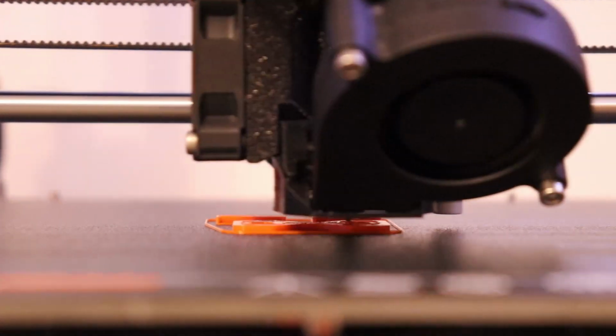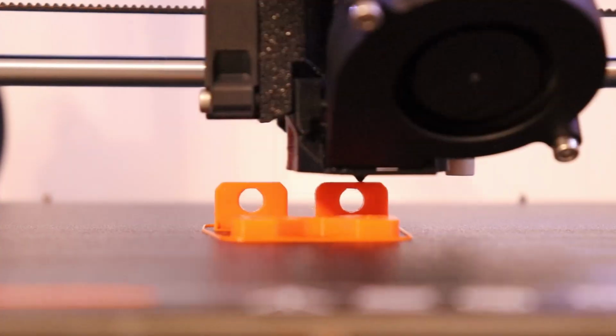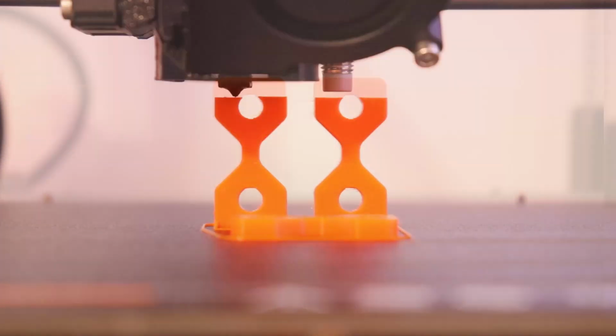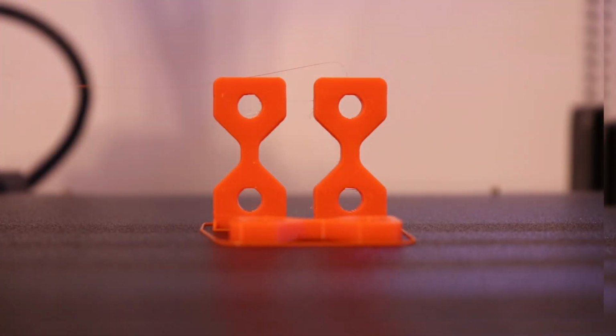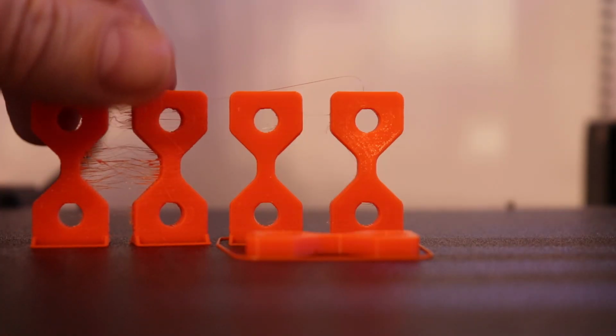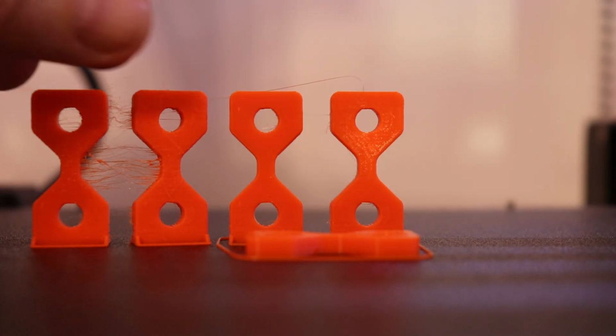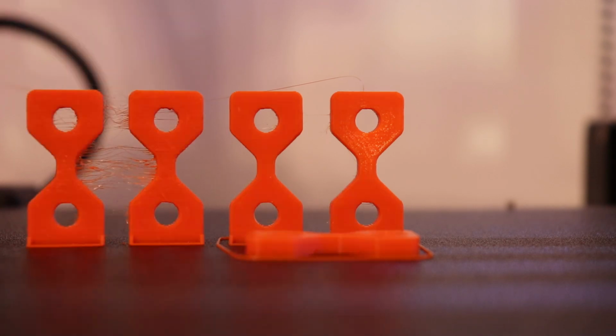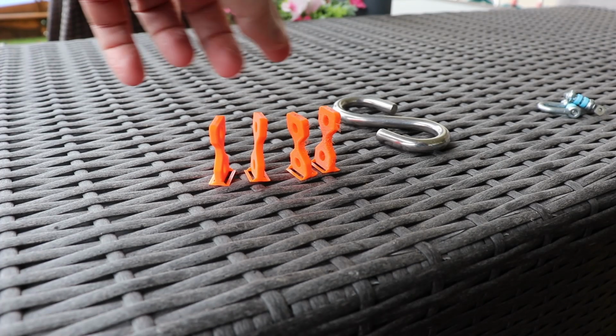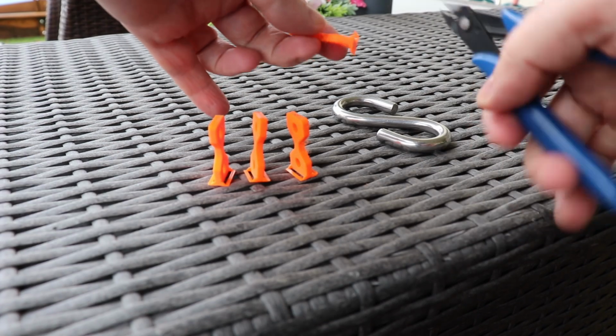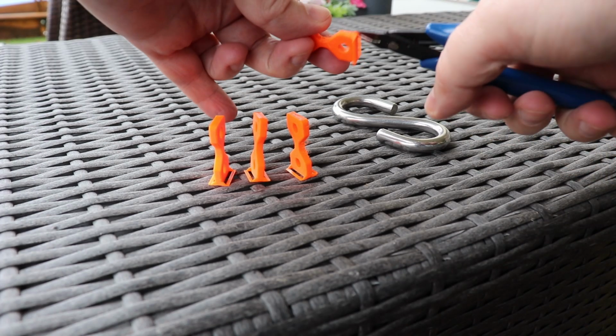And I use the same settings and G-code as with the previous printing. And as you can see, much better results, almost absolutely no stringing. But I want to test the layer adhesion too. And here they are side by side. These are my test specimens to check the layer adhesion. Only I have to remove these temporary supports.